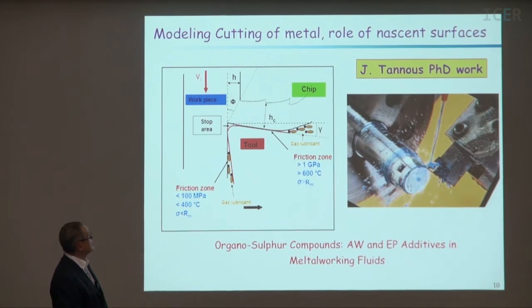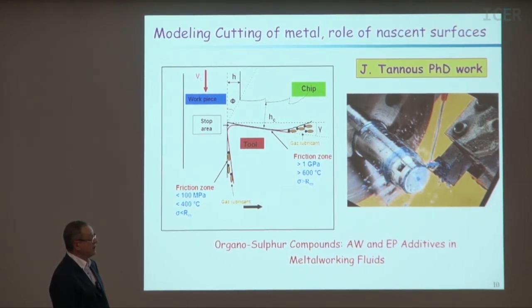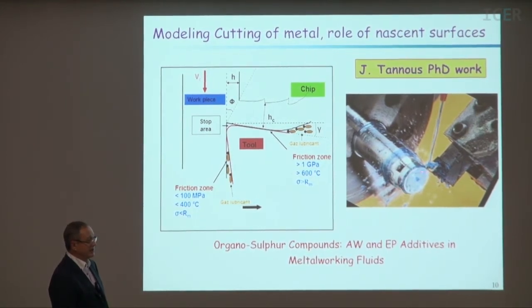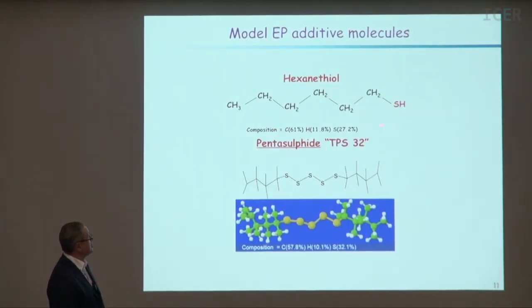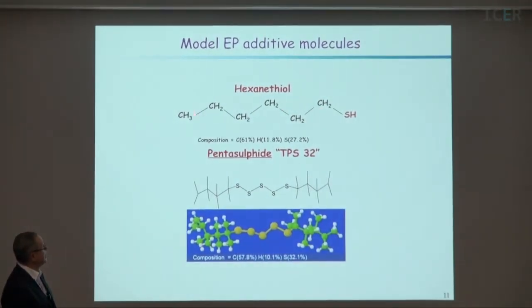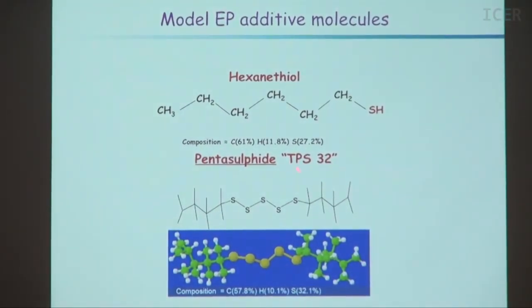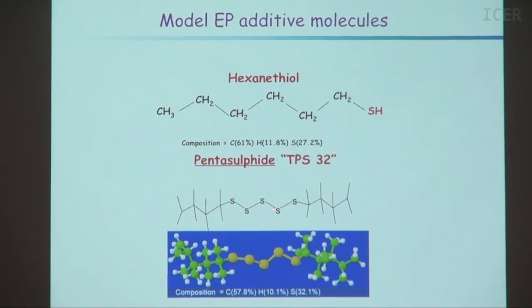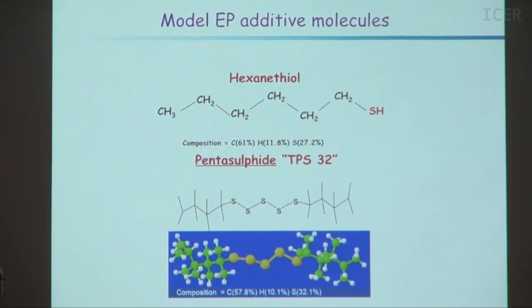For example, this is a problem of cutting of metals. In the cutting of metals, you have nascent surfaces formed, and the surface reacts immediately with the molecules which are in the lubricant. So we try to simulate this very complex situation. So we use 2 molecules here. This one is hexane-thiol, and this one has a more complex structure with a sulfur, but this is an industrial additive used for cutting.